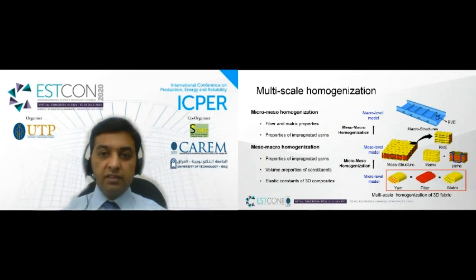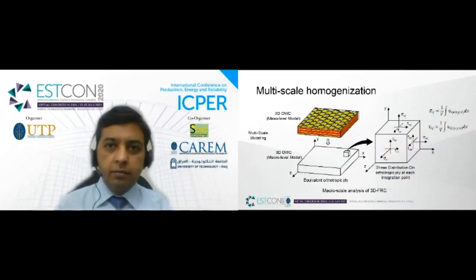So here we are considering 3 different scale levels. Number 1 is the micro level, which means that we are talking about individual fiber and matrix in impregnated yarns. Number 2, the meso level, which means the impregnated yarns and matrix in the RVE. And the final, the macro scale, which means the orthotropic material at macro level. So in this paper, these elastic constants are predicted using both an analytical and numerical method and compared with experiments. At macro level, the 3D composite is considered as orthotropic material. Using multi-scale modeling, we can predict all the 9 elastic constants of these 3D composites. These elastic constants can be used in the macro scale finite element analysis of these 3D composites under different mechanical loads.